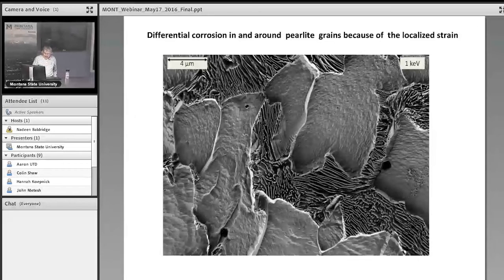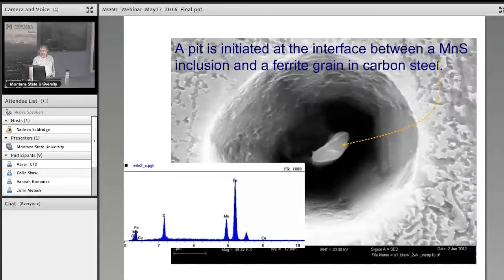So here is another example. This is a manganese sulfide inclusion. Remember I said anytime you have an impurity, it strains the local environment. So it starts pitting away. You can see there's a pit evolving. And when you look at the EDX, you can see manganese and sulfur, manganese sulfide, equal amount of sulfur, equal amount of manganese. And you can see iron because EDX really is not localized here. It takes information from the surrounding.